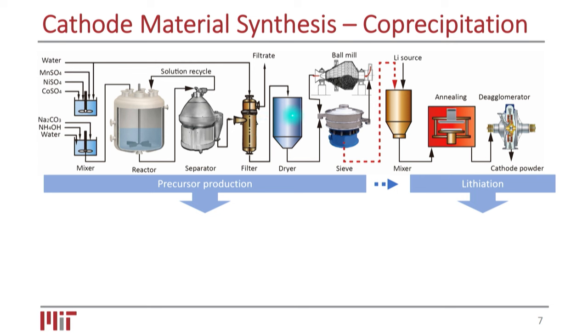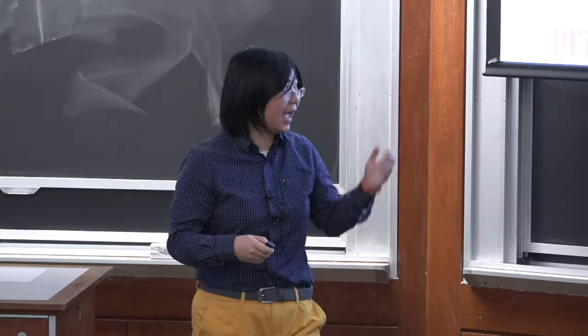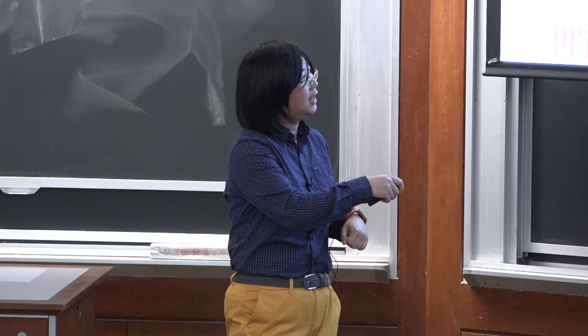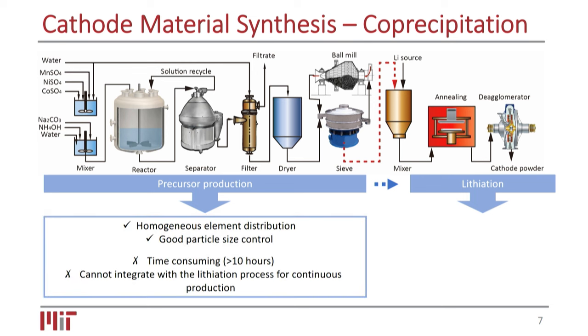And via some separation of the liquid phase and the particles, we can get the precursors out. And in the next step, we call this lithiation, meaning that a lithium source in the form of oxide and salt will come into play, and we will have a solid state mixing between the lithium source and the precursor. And this process, due to its solid state mixing nature, is expected to take a long time, so we do have a high temperature, long time annealing process in place.